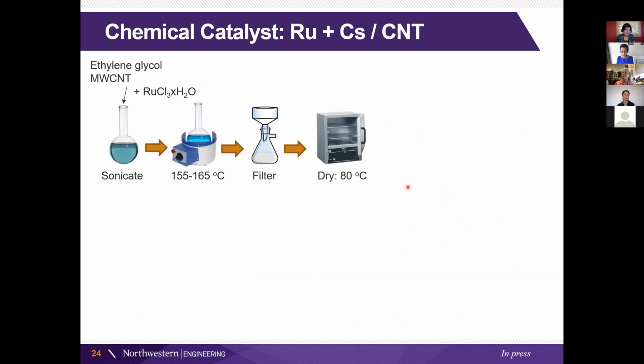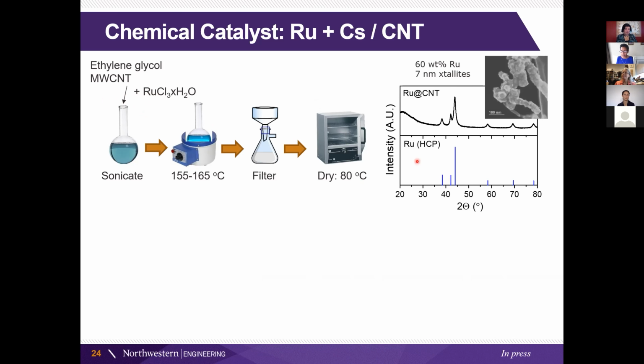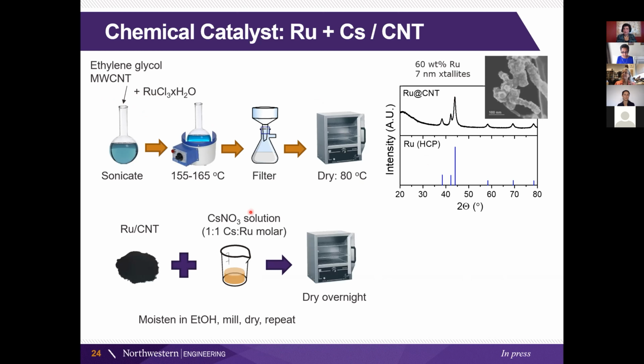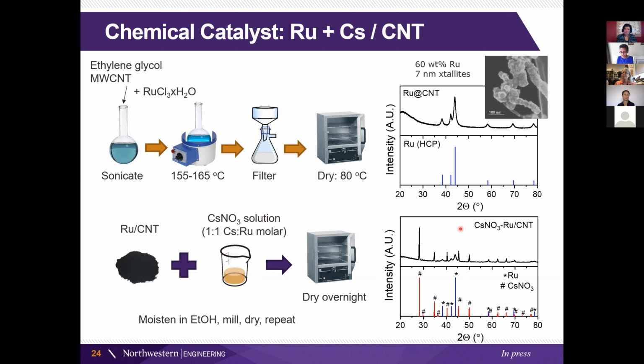And just to show you a little bit now, a little bit of chemistry of what we do. So we're using a ruthenium-based catalyst, depositing that on some multi-walled carbon nanotubes, but we also do this on cheaper Vulcan carbon. We prepare that electrocatalyst. This is the chemical catalyst material, and we get some small crystallites here. We have a relatively high ruthenium loading, but ruthenium is fortunately not quite as expensive as platinum. And then we promote it with cesium. This is not our recipe. There's quite a community doing this thermal conversion of ammonia to hydrogen. So we borrowed the recipe from that literature. We put the cesium nitrate on it. And so we get this cesium nitrate promoted ruthenium on carbon nanotubes.